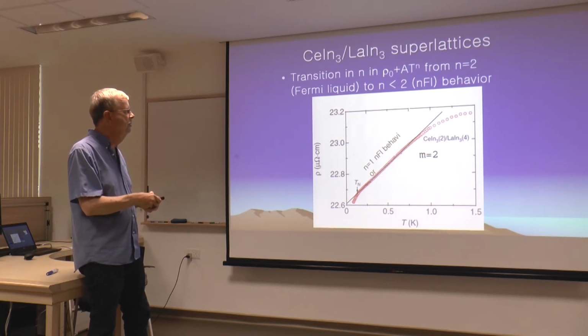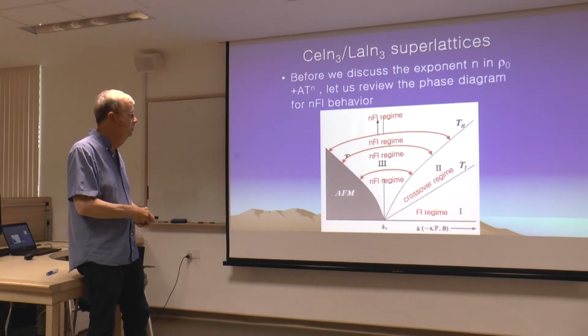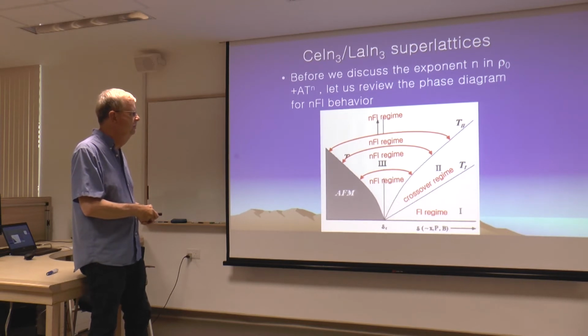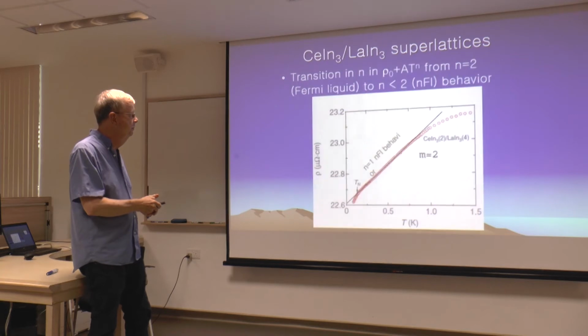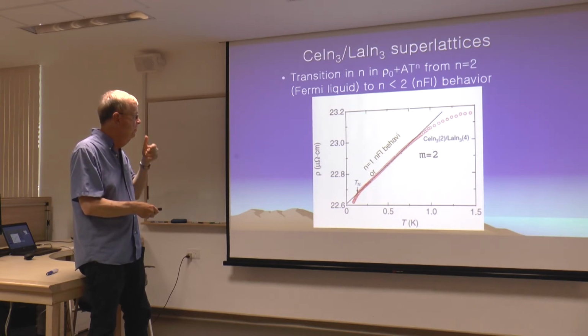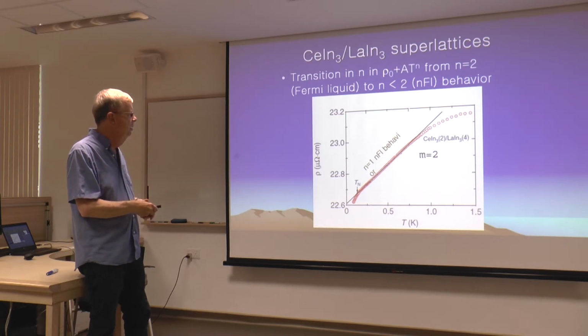And then at higher temperature, so I've tuned to here, at higher temperature I get to a crossover regime where I have neither simple T squared nor simple T to the 1. I have something in between. So here is at a tuning, this has been tuned by dimension. I'm at the non-Fermi liquid point from here up to here, and then it goes away to something else.